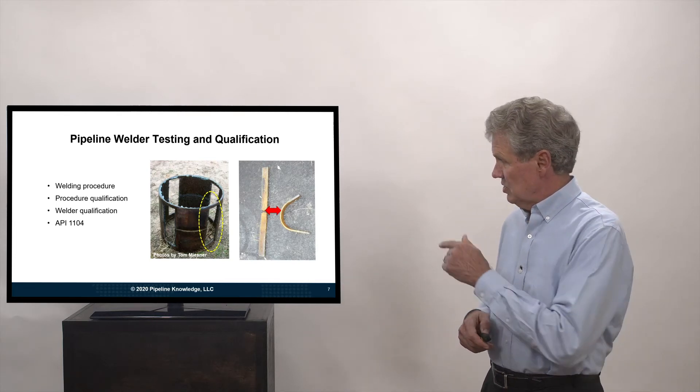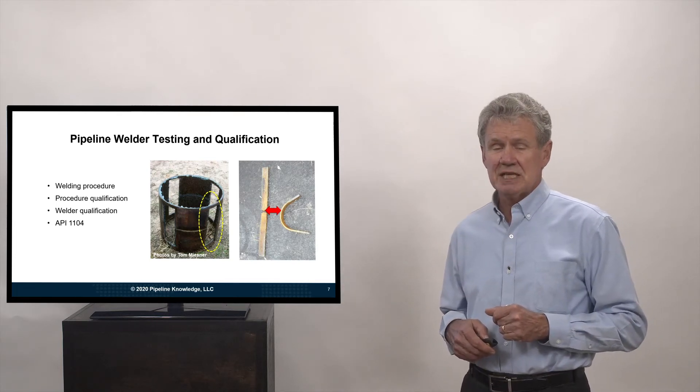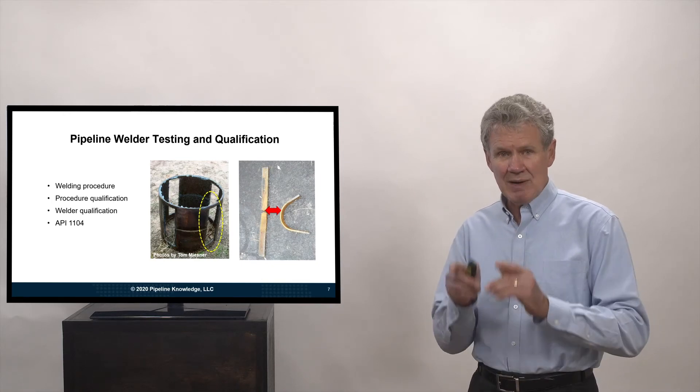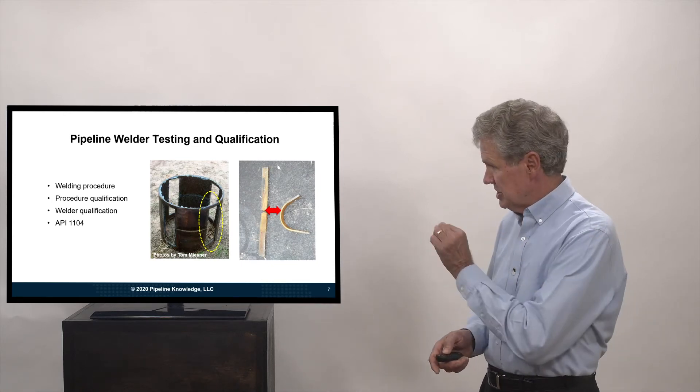Two different tests. The one on the left, we have basically taken the strap, ground it down, cut little notches where the weld is, and pulled it to make sure it breaks at a force that would be stronger than the parent material of the pipe.